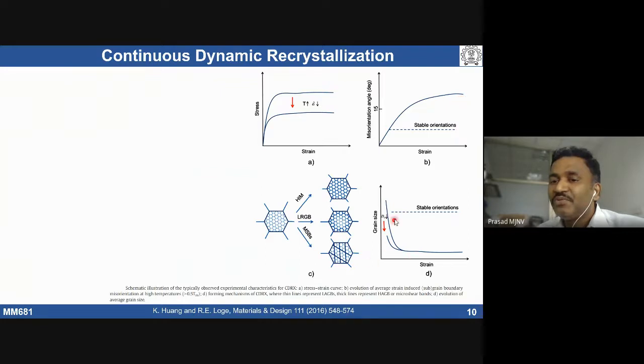If you look here at the initial grain size, we have very coarse prior grains. When you deform it, with further deformation we see a steady state grain size is going to be developed. What is the effect of the initial grain size? Say my starting grains are, one 100 micrometers, the other 10 micrometers. The final grain size is immaterial. What you are getting is the same. It's not going to depend on your initial grain size.